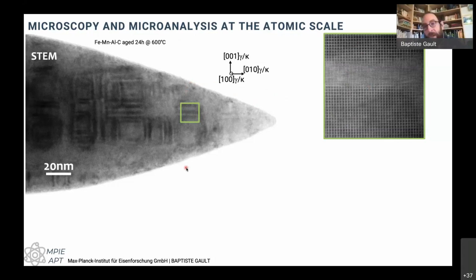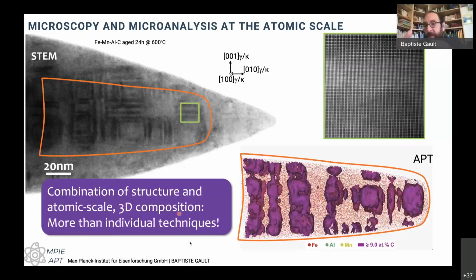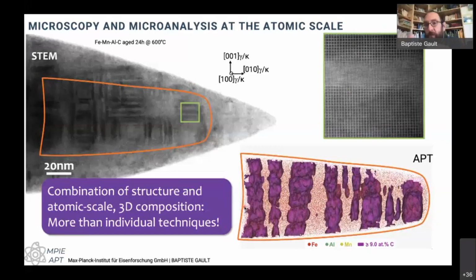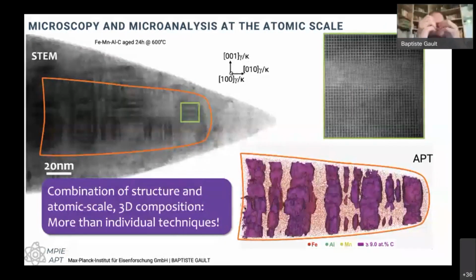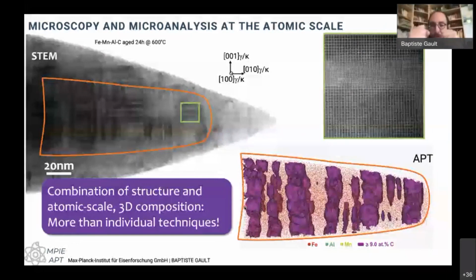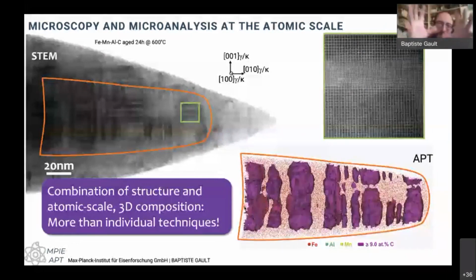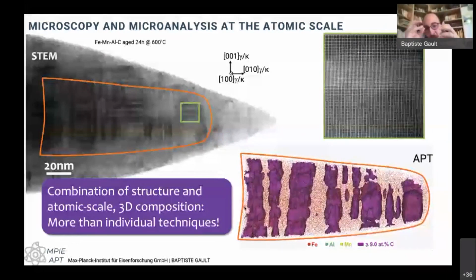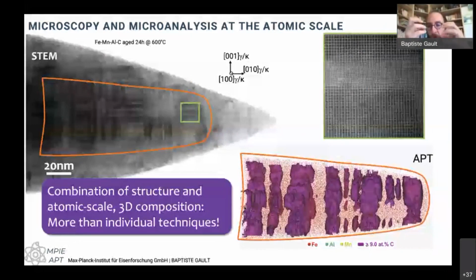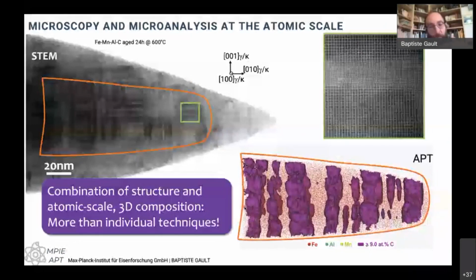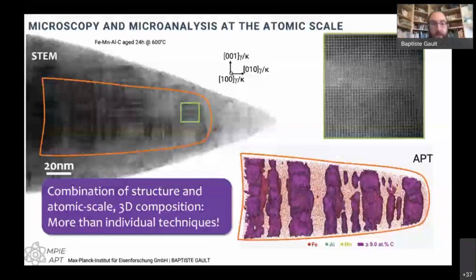And then the capabilities to measure composition in the TEM are also sometimes limited. So what we may want to do is combine this information on the structure with the information we can get, for example, from the atom probe, where we might not have exactly the same accuracy spatially. And again, I'll get back to this, it's still the introduction part, but we get locally what is the composition of the material, including, for example, carbon and aluminum and manganese and iron.